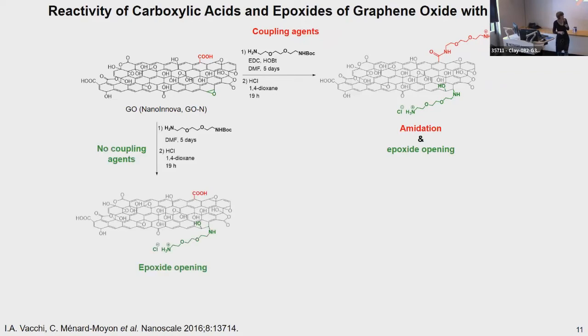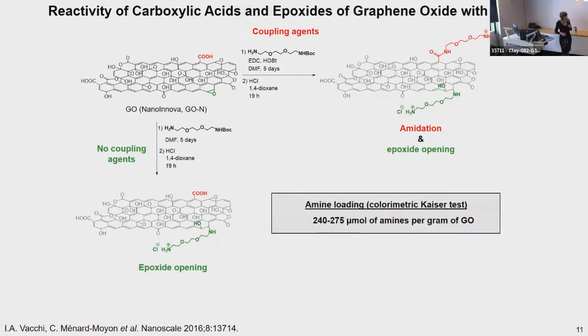In parallel, we also performed the same reaction, but without any coupling agents. So in this case, only the epoxide opening occurs. We assessed the level of functionalization using the colorimetric Kaiser test, allowing us to determine the amine loading, which was in a range of 240 to 275 micromoles of amines per gram of graphene oxide in both cases. So you see that there was not much difference in terms of amine loadings between the two different conjugates.